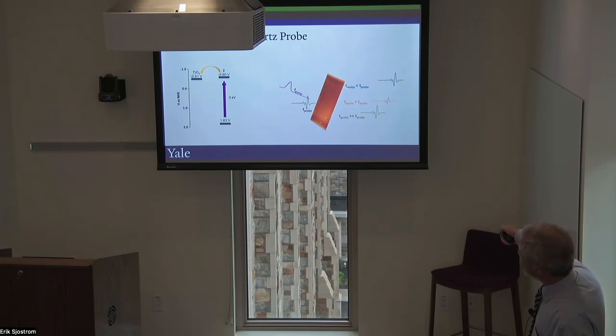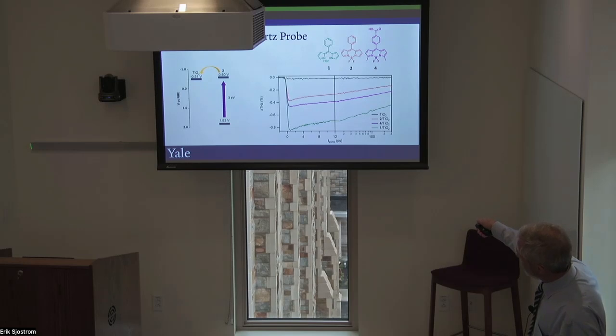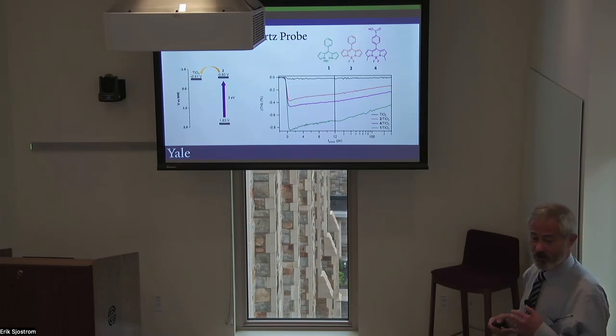And so if the pump pulse is after the probe pulse, we don't see any attenuation of the terahertz beam. If the pump pulse is immediately before the probe pulse, we see an attenuated terahertz signal. And then if we wait a long enough time, it comes back. And this is what we see. Time zero is when we give the optical 400 nanometer femtosecond pump pulse. And we see very rapid absorption of terahertz from all of these molecules bound on the surface, which is telling us that there's ultrafast electron transfer in all of these cases on a femtosecond timescale. And then it recombines on a much longer timescale, hundreds of picoseconds. So we have a long-lived charge injection with these molecules.